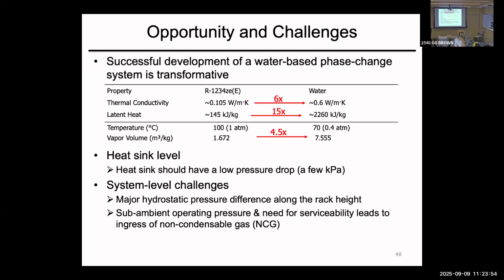But the challenge is that water boils at 100 degrees C. If you go to lower pressure, the vapor expands so much that at some point the performance even drops below that of the refrigerants. So the question is, can you address that? Obviously the heat sink you saw does, because we immediately exit that massive amount of vapor through the membrane. So obviously that was a breakthrough.